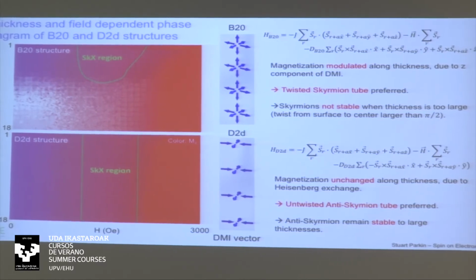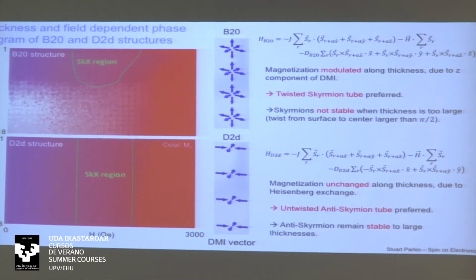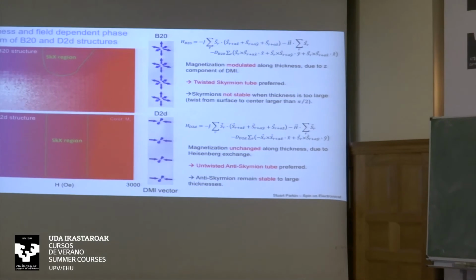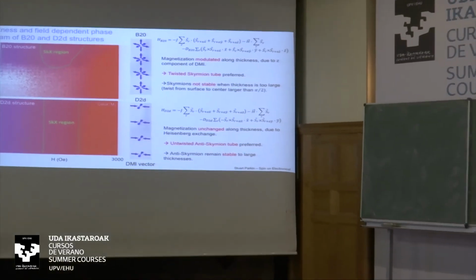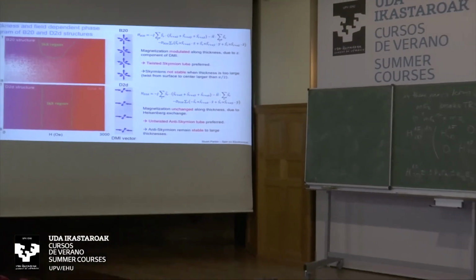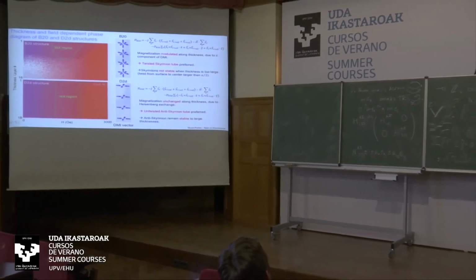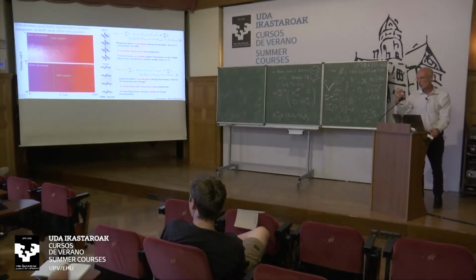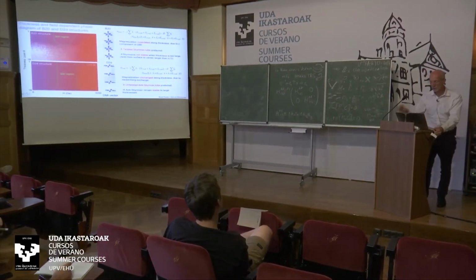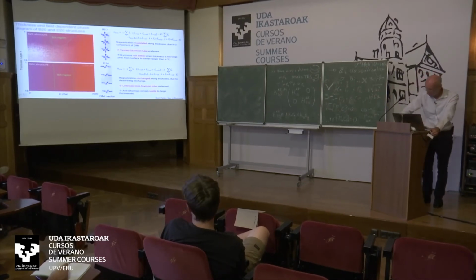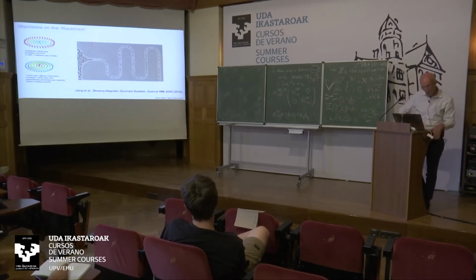So the skyrmions go from 100 nanometers in these thin lamella to more than a micron in size for thick lamella, and we can image them using Kerr microscopy and magnetic force microscopy. It's extremely interesting, and we have a detailed prediction of how the helical period and the size of these antiskyrmions will vary with the thickness of the lamella, which it turns out to be even more interesting than I have presented.